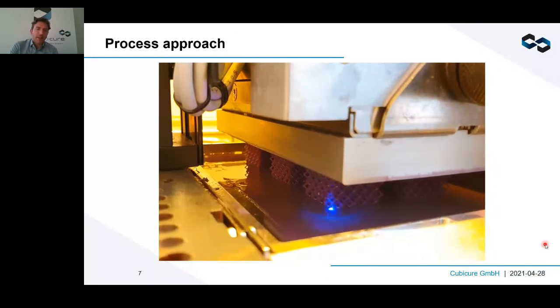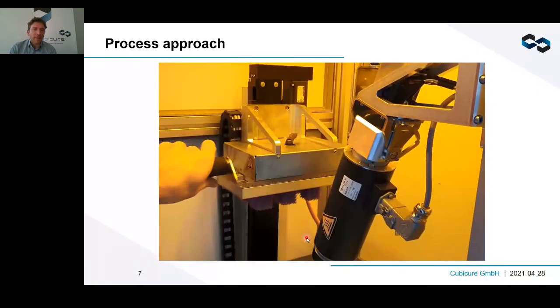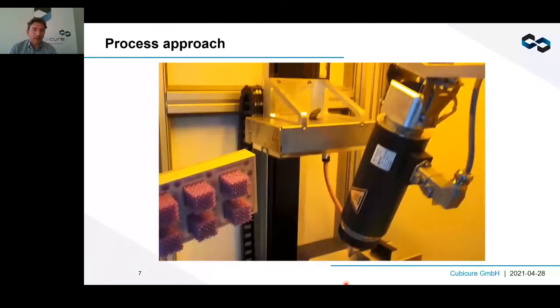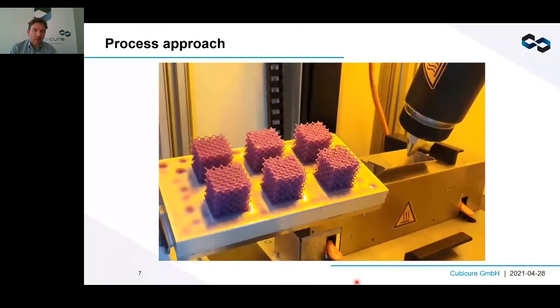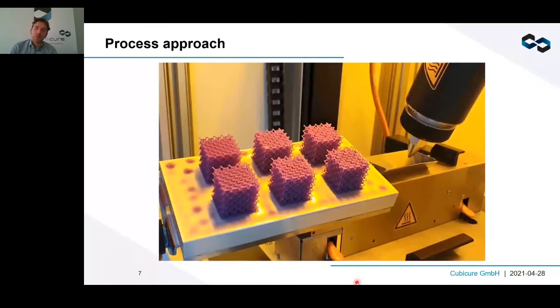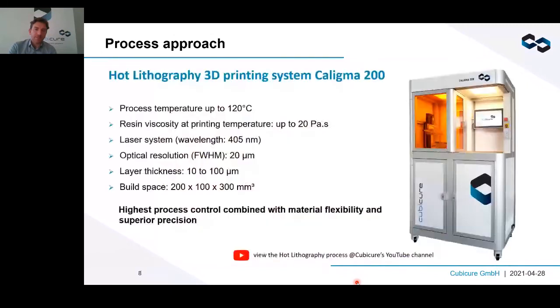So in this vat, we do not have a full vat of material, but we always provide this thin layer of resin. And in this thin layer of resin, the light information is put in, and then with very fine detail we can write objects and build them in the third dimension. And the good thing is this is working for soft materials the same way it works for hard materials. So the process window is really quite broad, also in terms of the final material properties we can process here.